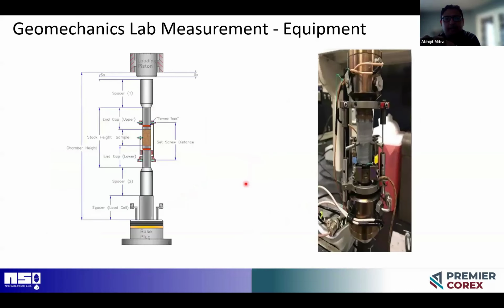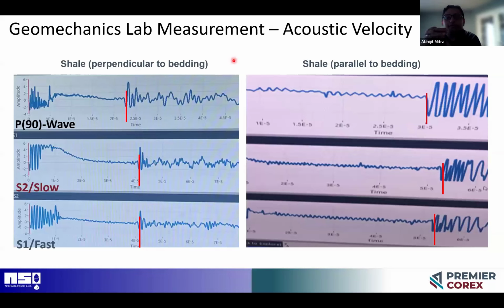In the next slide, I'm showing you the experimental setup. The sample sits in the middle between two end caps, and each of these end caps houses a few piezoelectric transducers, which have the ability to send and receive ultrasonic velocity signals, at a frequency close to the megahertz. Compared to that, your sonic tool has a high kilohertz frequency. So we can transmit one compressional and two shear wave velocities through the plug sample whenever we are running the triaxial test. And then we also have what we call the deformation transducers to monitor the change in sample length and sample diameter.